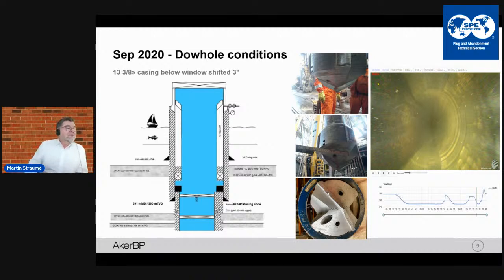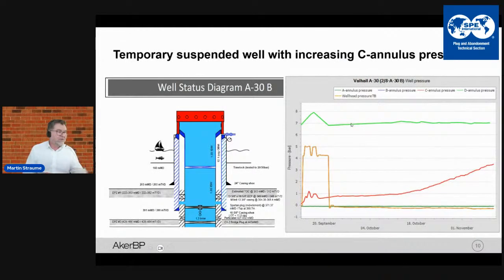When we got through the bismuth plug, we could see that the gas started to come. So this was proof for us that the bismuth plug had been holding. We had seen no bubbles during those 2 years. We knew that the D annulus, as you can see out here, had maintained 7 bars, about 100 psi. So there was no change to that.